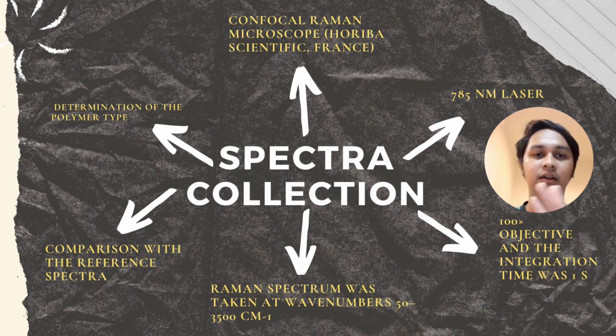Before we use the Raman spectroscopy, there are several things we need to consider. For the spectra collection, this analysis used a confocal Raman microscope from Horiba Scientific, France. The wavelength used is a 785 nanometer laser, and for the magnification, the research used a 100 times objective, and the integration time is 1 second. The Raman spectrum was taken at wave numbers between 50 and 3500 cm-1.